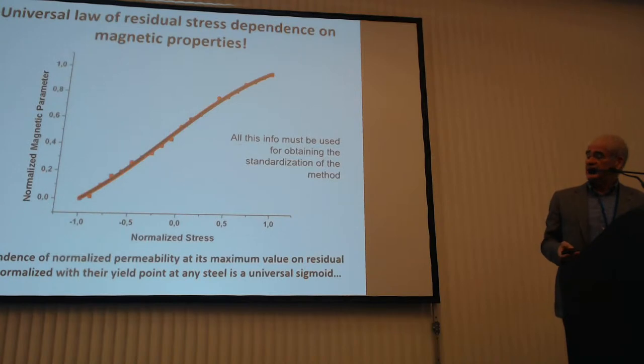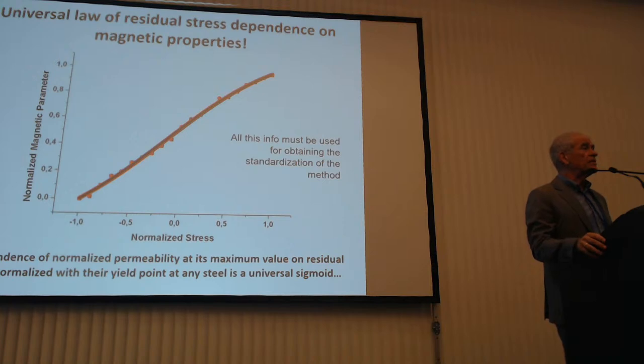Furthermore, I have to say that all these curves, if normalized with respect to the yield point of each steel and the maximum amount of the magnetic property under measurement, result in a universal law. This means that all magnetic stress calibration curves collapse into one single universal dependence of magnetic properties on residual stresses. What does it mean practically, apart from a good fabrication?